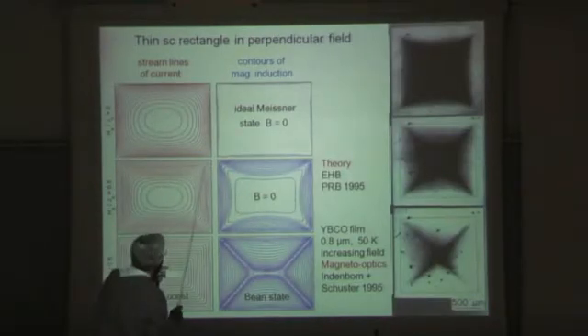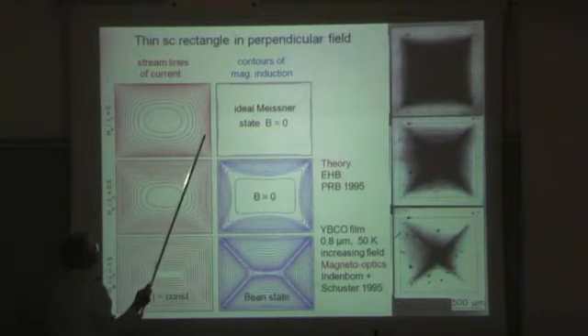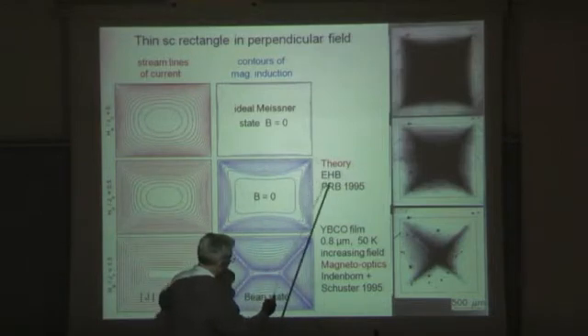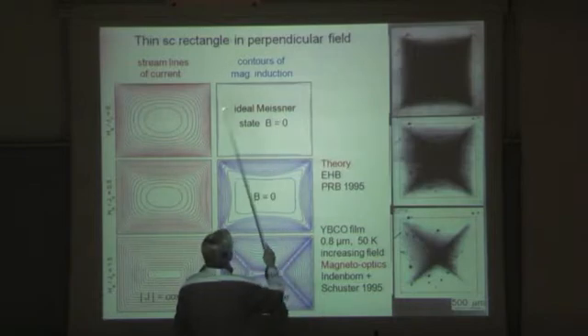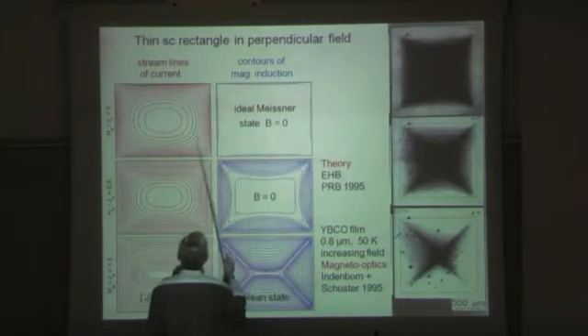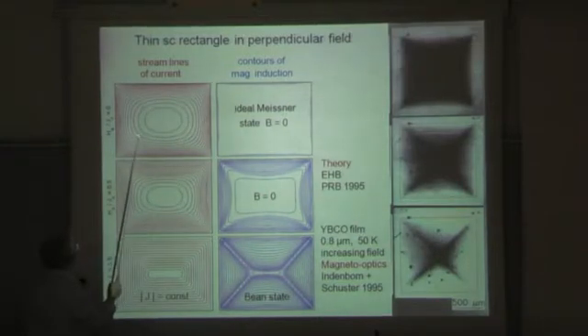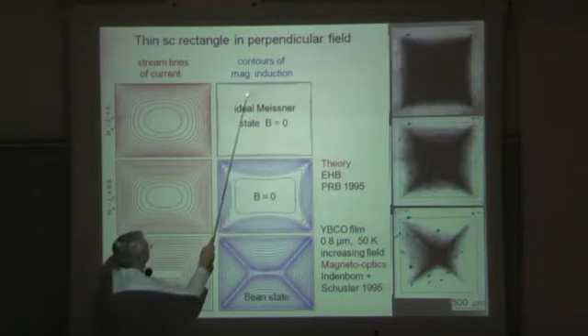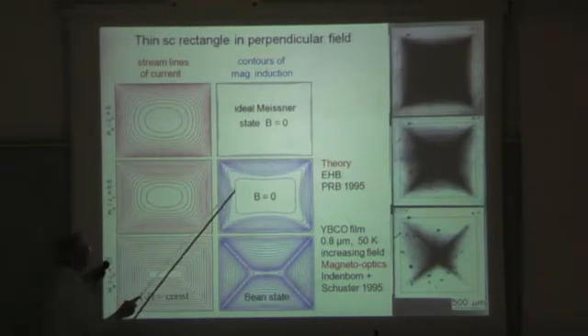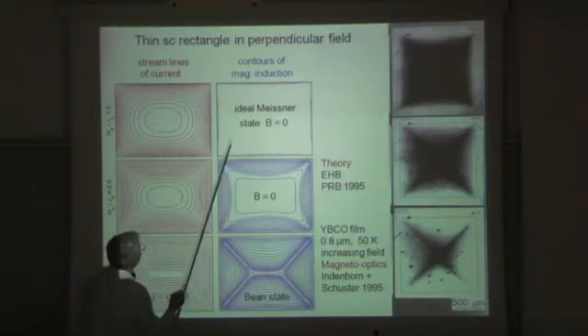Another geometry is when you have a thin rectangular film. In the beginning, pinning keeps the vortices out. And now you increase the applied field, then first you have the ideal Meissner state. And this is a current distribution, the current streamlines for this Meissner state. This current generates a magnetic field in this plane, which is exactly opposed to the applied field. So it's a constant magnetic field, but with sign opposite to the applied constant magnetic field.